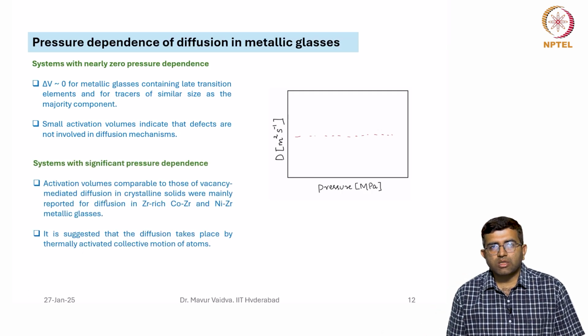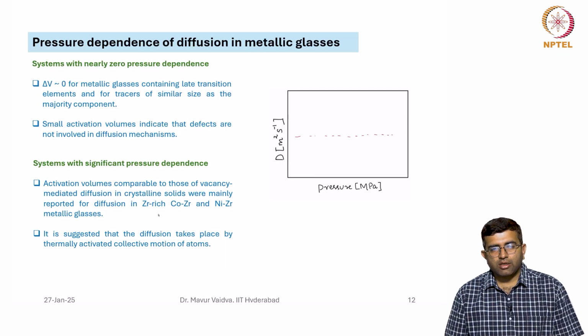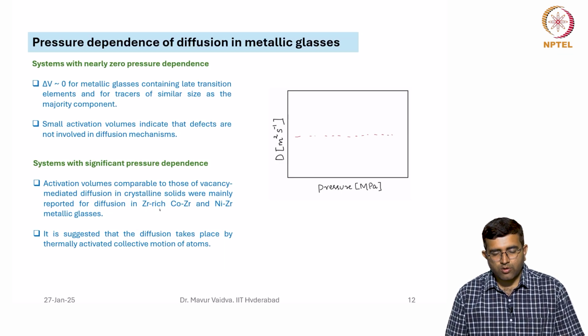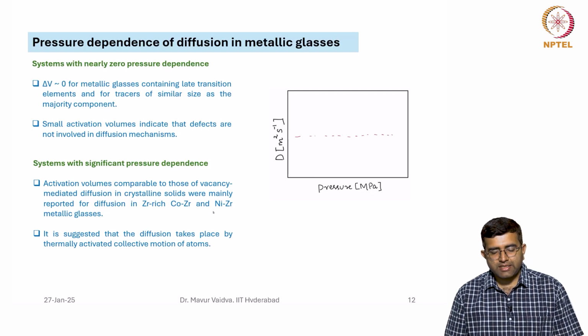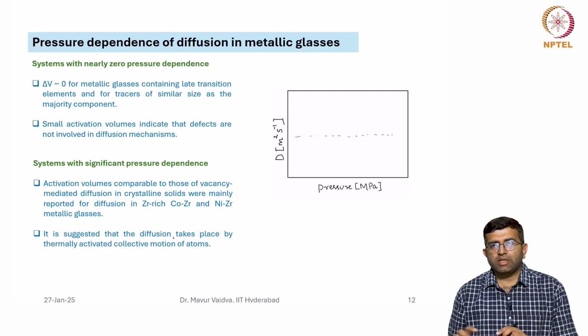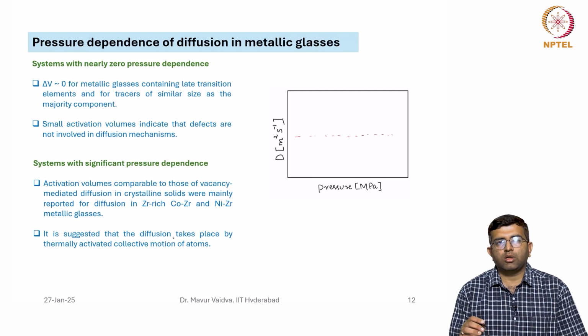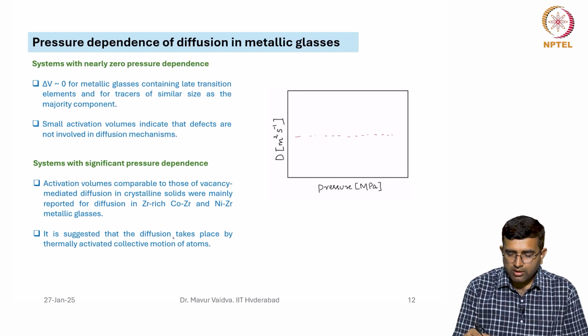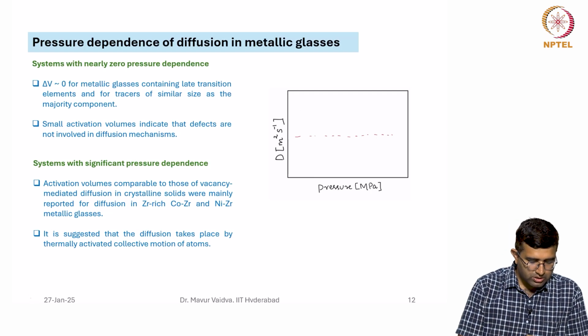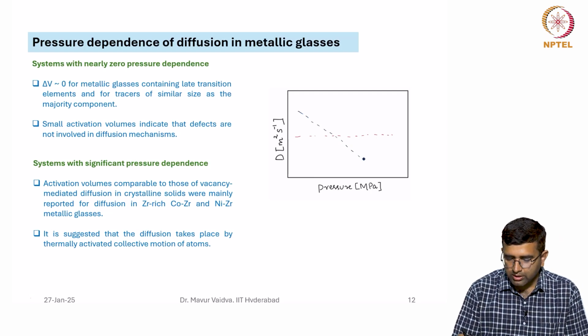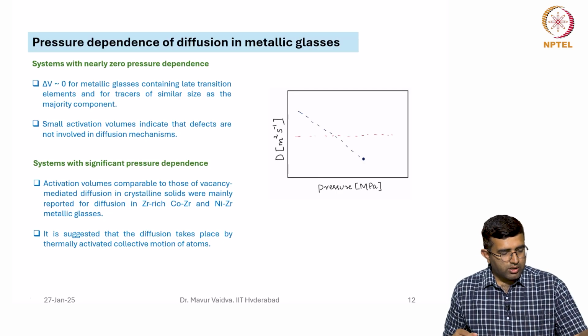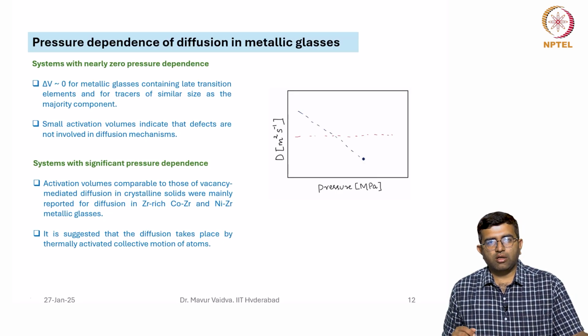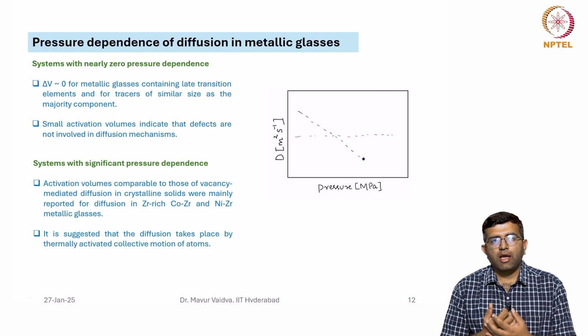Then there are systems with significant pressure dependence. Their activation volumes are comparable to those of vacancy mediated diffusion in crystalline solids, and this is observed for zirconium rich CoZr and NiZr metallic glasses. So if you have an activation volume which is non-zero, then you may have a variation which may look like this. This suggests that defects are involved in the diffusion mechanism.